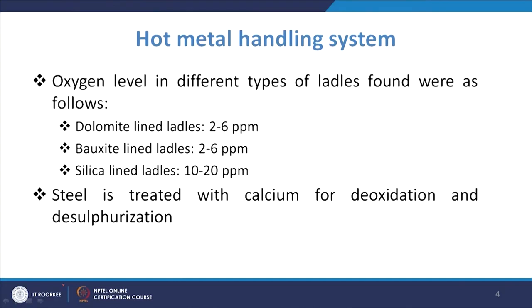Now, steel will be treated with calcium for the deoxidation and desulfurization. So, in most of the cases we try to have the minimum amount of oxygen, as well as sulfur is also deleterious for the quality steel. So, we also try to treat with the calcium for the deoxidation and the desulfurization. So, that is what is normally the practice in the industries by using the calcium.